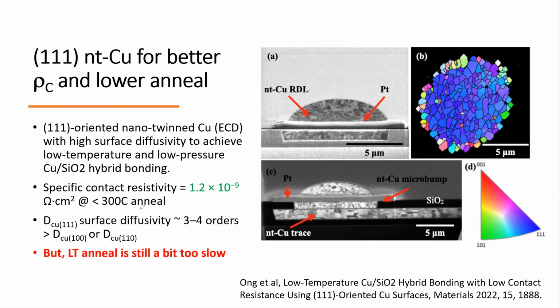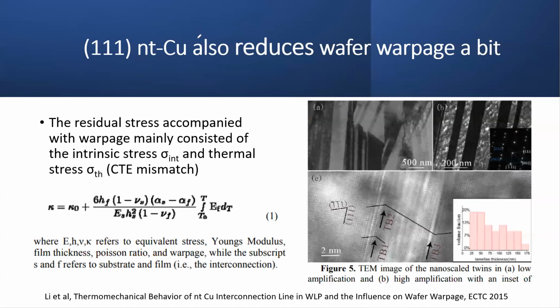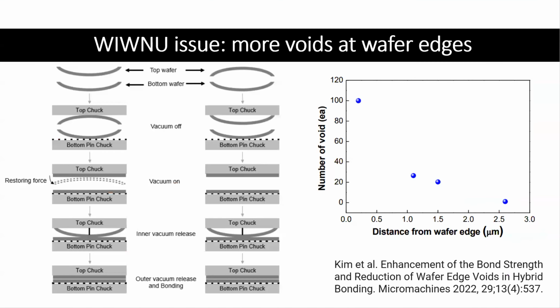So yeah, and then they say they could do it at a lower temperature. Except at low temperature, you require longer time, which is not good. You could do it, say, in seconds, but they turn out to need minutes or longer to achieve that. So it's an idea, and that gives you something to do to improve your process. And it also reduces wafer warpage. It turns out this material, if you've done it right, they figure could reduce the warpage in a way. All right, so this is how they did the experiment.